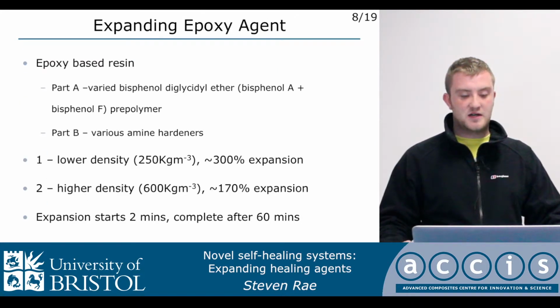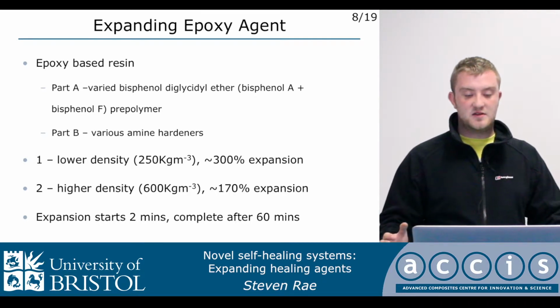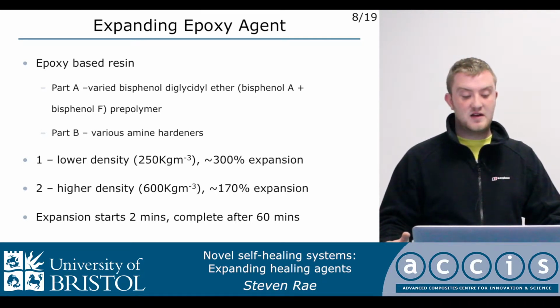The first system we've been looking at is an epoxy resin-based system. Two parts. Part A uses bisphenol A and bisphenol F, and Part B is various amine hardeners, and this comes in two forms. We can have a low density foam produced that gives a higher expansion, about 300%, or we can have a higher density foam produced with a lower expansion, about 170%. With each of these systems, once the two parts are mixed, expansion will start within 2 minutes and usually be complete after 1 hour. And it takes another 5 to 6 hours to fully cure the healing agent.